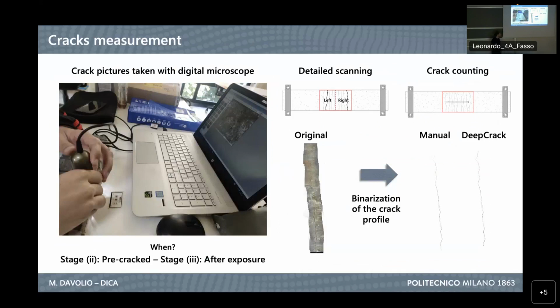Then we measured the crack width of the specimen by means of a digital microscope. We did both a detailed scanning of just 2 cracks from each specimen, as you can see from the scheme, and in some cases we counted the number of cracks because we expect a multiple cracking regime from the UHPC.